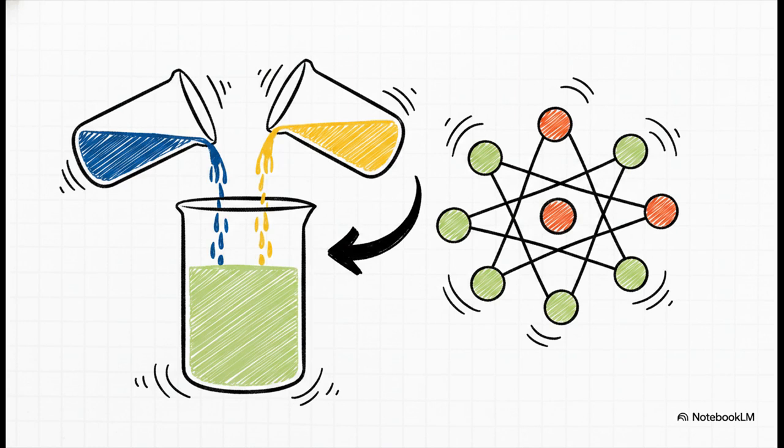To wrap your head around how we force foreign atoms into a pure metal, think about a super common liquid analogy. If you mix water and alcohol, they completely dissolve into each other, right? They create a perfectly homogeneous liquid solution. Well, solid metals can do the exact same thing. When we add an impurity, we're making a solid solution. The element that does the heavy lifting, the one with the greatest amount, is our solvent or host atom. And that tiny bit of minor element we sprinkle in, that's the solute. Those impurity atoms just disperse randomly and uniformly throughout the whole solid structure.